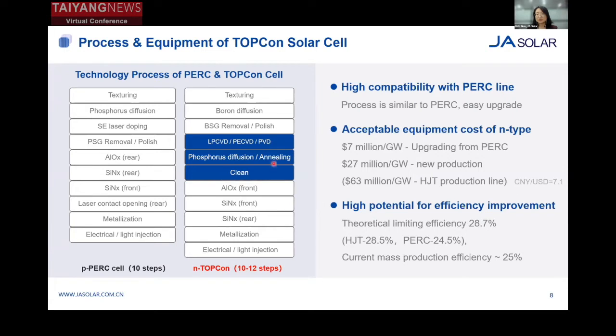This equipment is used to form the oxide and polysilicon layers. Now there are mainly 3 technical routes: LPCVD, PECVD, and PVD. The upgrade investment is small, only $7 million per gigawatt. And if you build a new line, it will cost about $27 million per gigawatt. On the contrary, the equipment cost for HJT is much higher. It's about $63 million per gigawatt. So easy upgrade, acceptable equipment cost, and high potential for efficiency improvement will boost the development of TOPCon technology. However, there are still some challenges for each technical route.